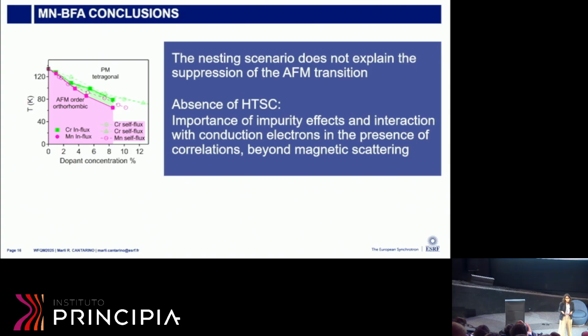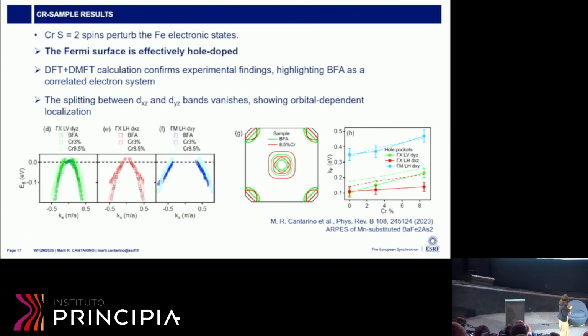Now I will turn to the chromium case. What we see for chromium is already different. We have seen that the Fermi surface is actually hole doped, so the hole pockets are getting bigger. This was reproduced by DFT plus DMFT, which is a sign that the system is in fact correlated.